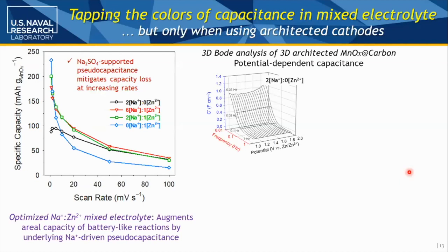So if we've got pure capacitive response with our sodium electrolyte, you can see up here our slowest frequency, 0.01 hertz. We're looking at normalized capacitance. So this isn't a classic impedance plot. We're looking at it in 3D: capacitance, the frequency, and the potential. So we can see the nice capacitive waterfall across the entire potential window.